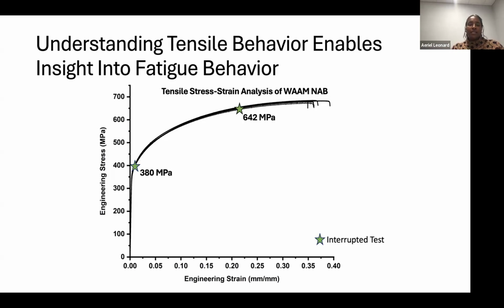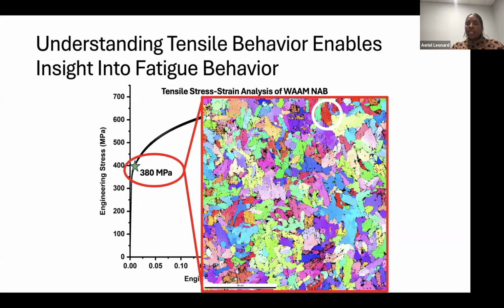So what we did was we tested several samples to get a true understanding of the tensile behavior, and then we interrupted tests either at the yield or near the UTS to see how the changes in strain changed the way dislocation behavior was progressing throughout the material. So we'll start with the sample that was interrupted near the yield stress. This is the as-deformed microstructure in this area, and this is the area of interest that we did a lot of deep characterization on to get a true understanding of the deformation mechanisms.